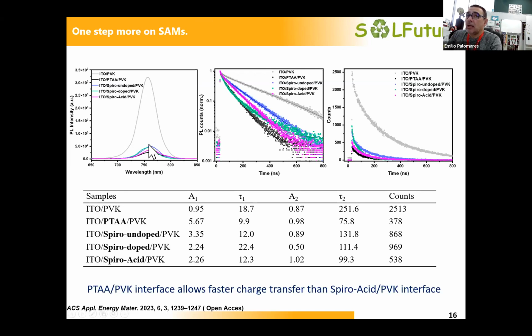So in a way, you are modifying the crystal structure of the first seeds of perovskite, and that makes the first few nanometers have a huge impact on the transport and also on the way that the charges are collected. But we haven't come up with a technique to study such things, other than luminescence. So the only thing that we can say is that when you have the SAMs, you actually have a very nice quenching or charge extraction of the charges at the interface between the perovskite and the ITO.